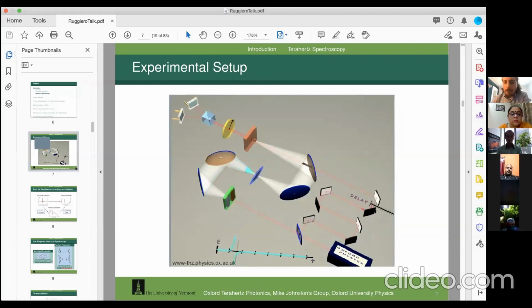Then what we do is the terahertz radiation hits this nonlinear crystal here, this orange crystal, and induces a birefringence. And then we overlap the 800 nanometer pulse on that crystal at the same time as the terahertz pulse is going, and we measure the optical properties of the 800 nanometer pulse.